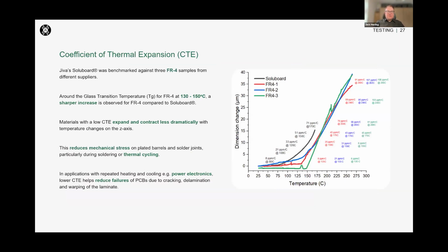So we've done some benchmarking against three random FR4 samples from different suppliers. And typically FR4 has a TG, a glass transition point of about 130 to 150 degrees C. And this means that they do tend to have a sharper increase around this TG when measuring the CTE compared to our material.